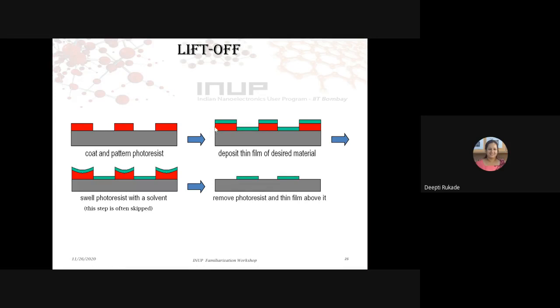This is normally used in cases where we do not have etching. There are materials like platinum, which itself is costly, and it is very difficult to get an etchant for platinum. If you have it, it is very costly. So for materials like that, we prefer using liftoff, where we do not have the etching, or getting an etchant is costly.